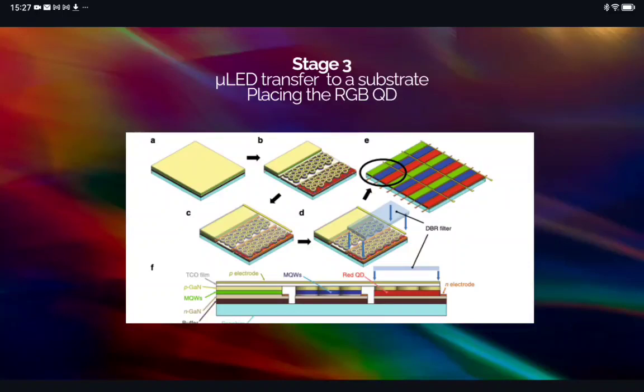There are several methods that have been developed to improve the efficiency of quantum dot-based micro LED displays. For instance, we can have a distributed Bragg reflector deposited on the bottom of the substrate to reflect the RGB light and enhance the output intensity. Second is utilizing the non-radiative Förster resonant energy transfer mechanism, which has also been developed in micro LED displays to improve the color conversion efficiency. The basic principle is to transfer the excess excitons generated in indium gallium nitride multiple quantum wells to quantum dot acceptors, thus producing more light from the quantum dots.